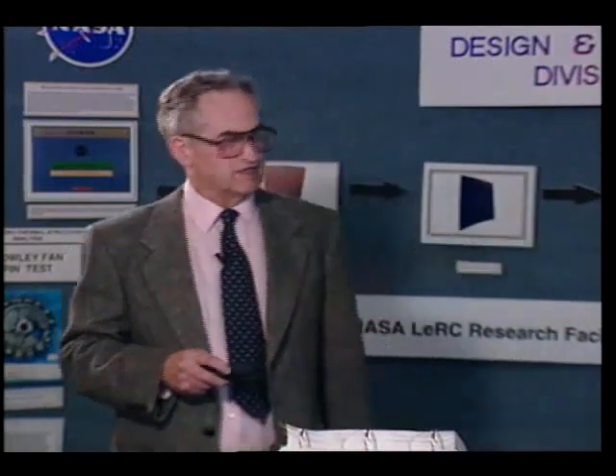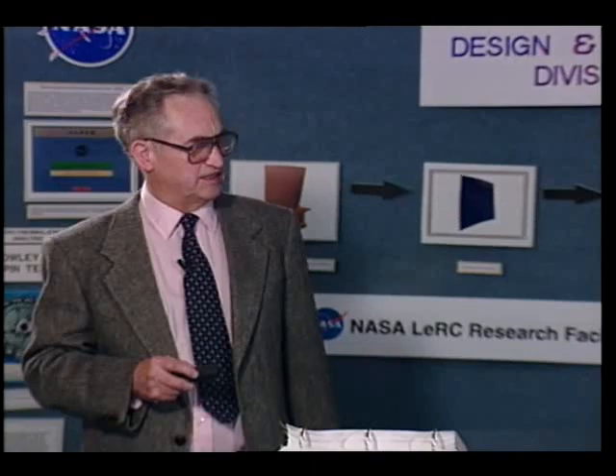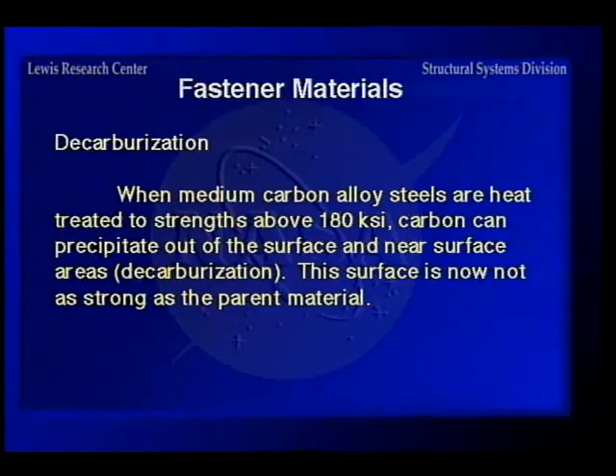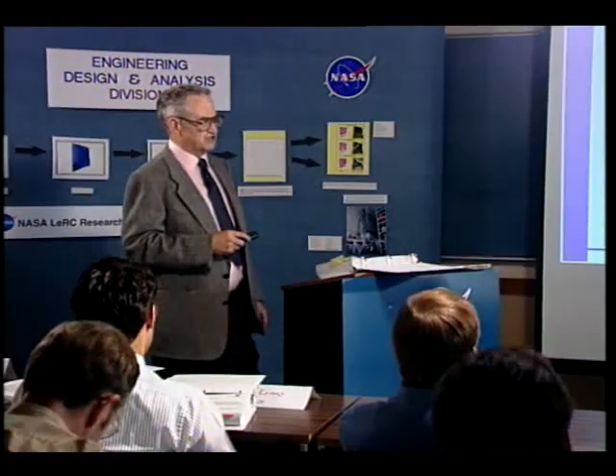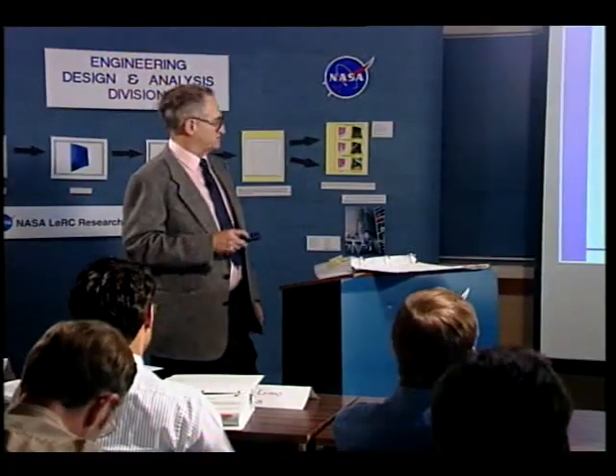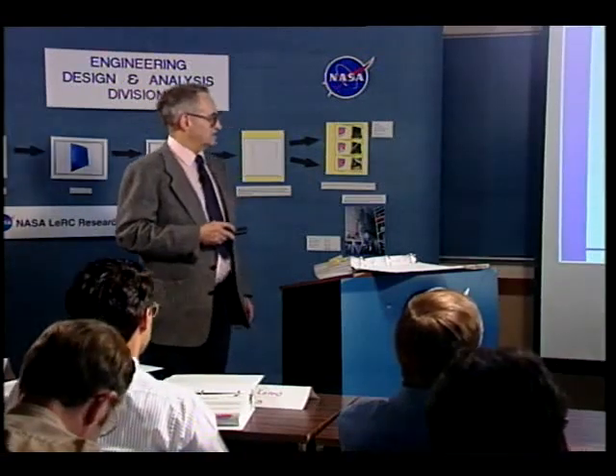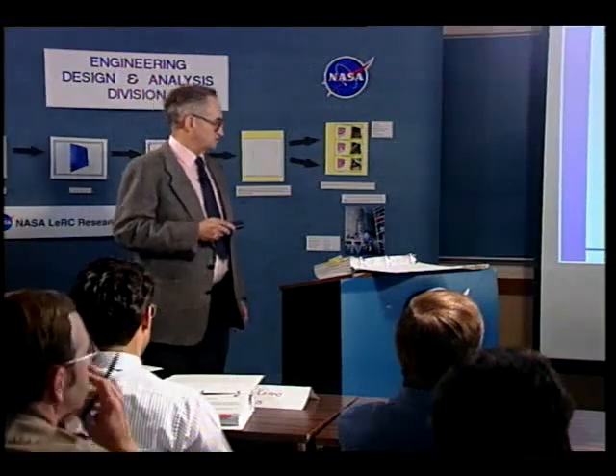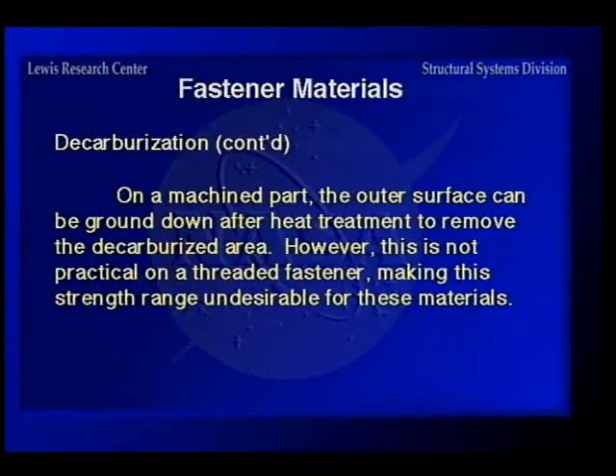Now here's another one that you can run into, although it's not that common, and that's decarburization. When you heat treat a carbon steel, you can actually precipitate carbon out on the surface. I would compare this to charred wood. Charred wood is very soft on the surface, because this is essentially what you're getting. You're getting a heavy carbon coat in the outer surface, and of course it's not as strong as the parent material. On machine parts, they sometimes just machine that off and they can use the part. But of course on a fastener you can't do that, so you have to be careful about decarburization. And once again, it's on strengths above 180 KSI.